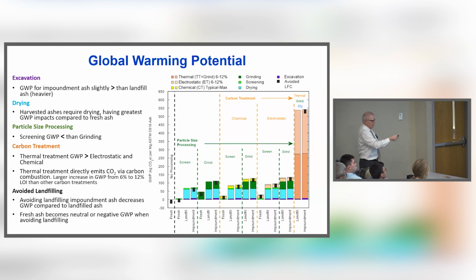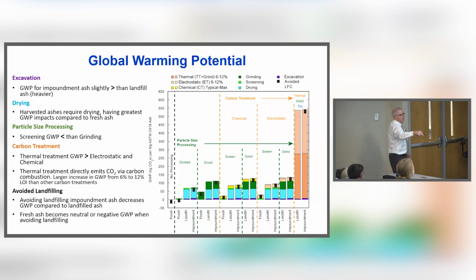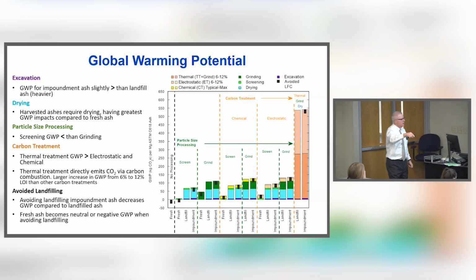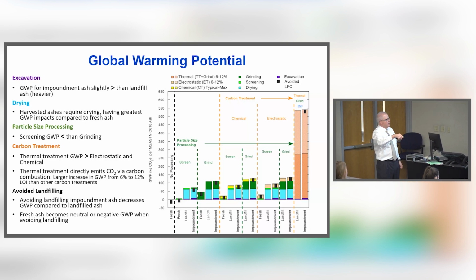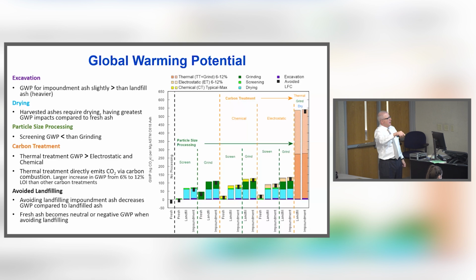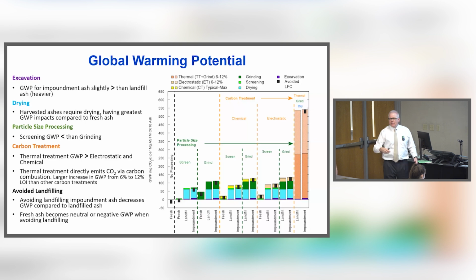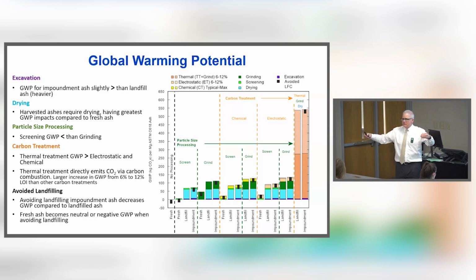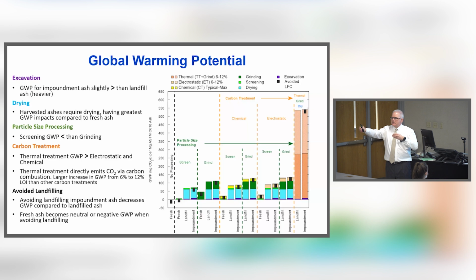And then I move from left to right. Okay, maybe I have my fresh ash and I have to screen it. I have my landfilled ash. I have to screen it. My ash from an impoundment or a basin, I've got to screen it. Then I'm going to be screening it and adding grinding in, then adding chemical treatment or electrostatic treatment or thermal treatment. And in each case, as the bars get bigger, that means my total amount of greenhouse gas emissions through processing the ash is getting bigger, all right?